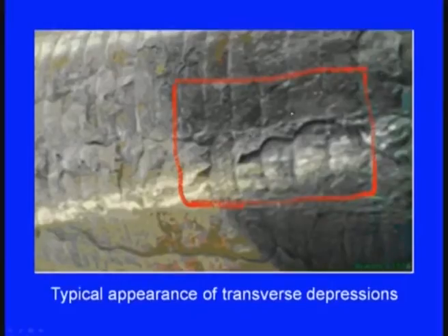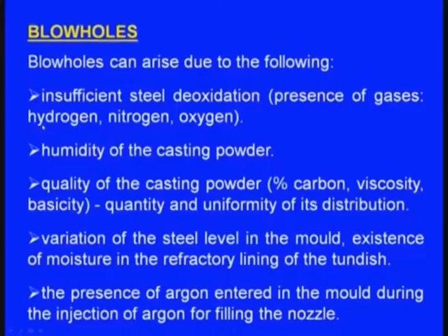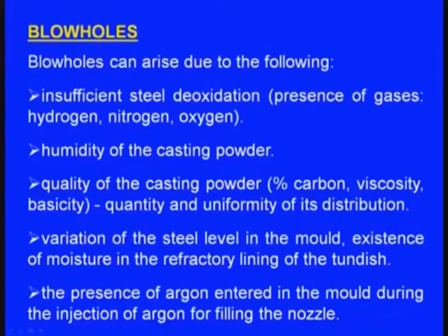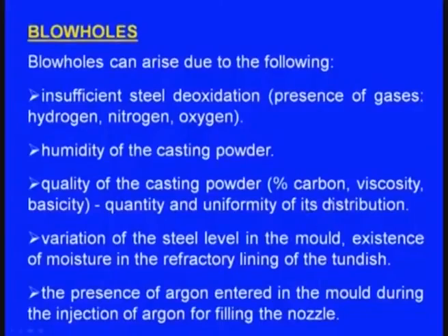Yes, this is the typical appearance of transverse depressions. Next one, blowholes. Blowholes can arise due to the following: insufficient steel deoxidation, presence of gases, hydrogen, nitrogen and oxygen. Next one, humidity of the casting powder, quality of the casting powder, percentage carbon, viscosity, basicity, quantity and uniformity of its distribution.